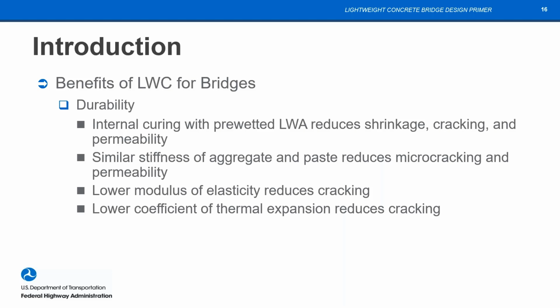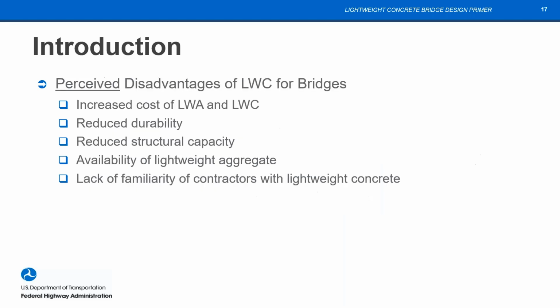So it's a significant benefit to using lightweight concrete or just internal curing, which we'll talk about later too. There's what's called elastic compatibility. That is, the modulus of elasticity of the aggregate is lower, which is closer to that of the paste, and it reduces micro cracking. And then also we have reduced coefficient of thermal expansion, and when combined with a reduced modulus of elasticity, that really does a lot to reduce cracking, especially early age cracking due to restrained shrinkage, but also thermal effects, which are significant, especially in decks that are restrained by girders.